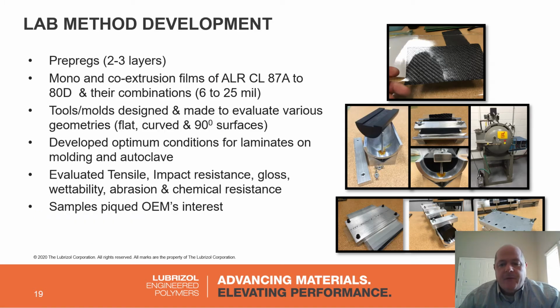Let me talk a little bit about some of the lab development we had done in Brecksville, Ohio. We had done different levels of prepregs, 2 and 3, different stack ups. We've tried many different films, from a monofilm to a co-extruded soft hard film, to different aromatic films. In these particular tests, as you can see, we did different geometries from curves to sawtooths to see if the film would move and form with the part and give you that clean surface. Again, these samples have piqued OEM interest, and we are in consistent development with getting these out into the field. But there can be other applications as well out there for carbon fiber.